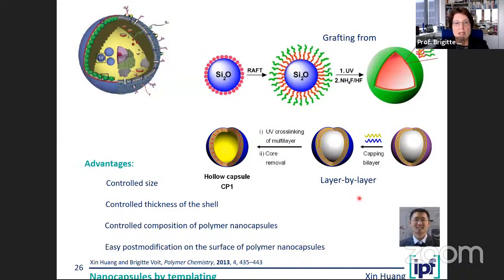A different approach to make the larger capsules is shown here. That is a templating approach for making capsules. So the other one was self-assembly. Templating is a bit different. You start with a silica particle. This defines the final size. You can do grafting on it to make finally a stable polymersome, or in this case, a capsule. You have again to do cross-linking to be sure that the capsule is stable. After that, you can remove the core just with ammonium fluoride, for example, and that gives you a capsule.